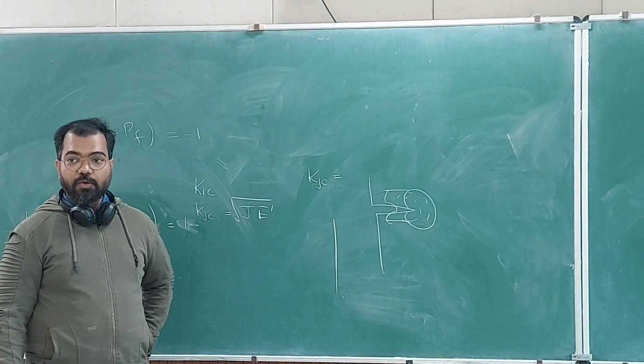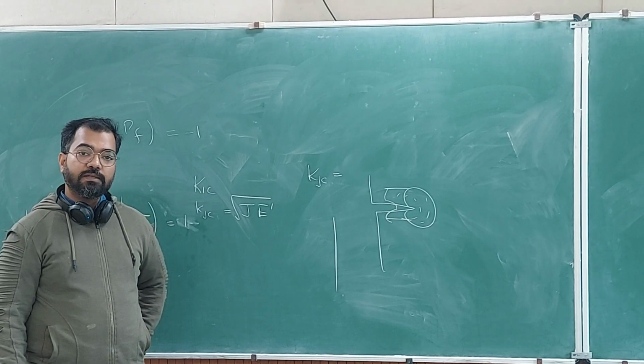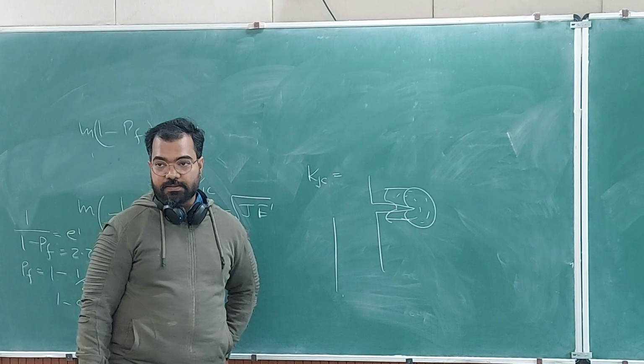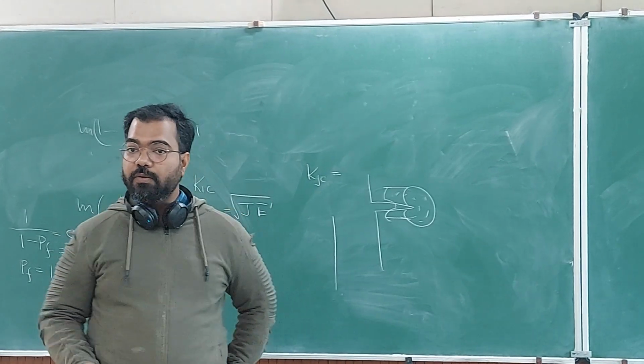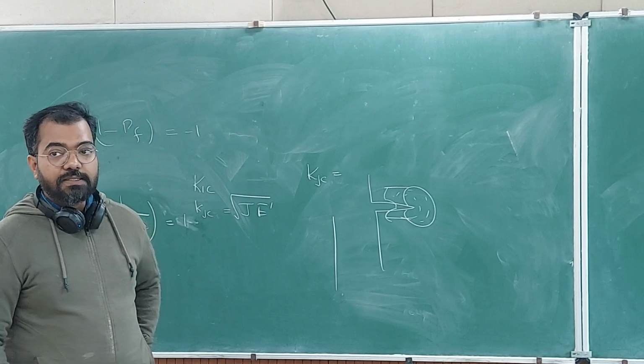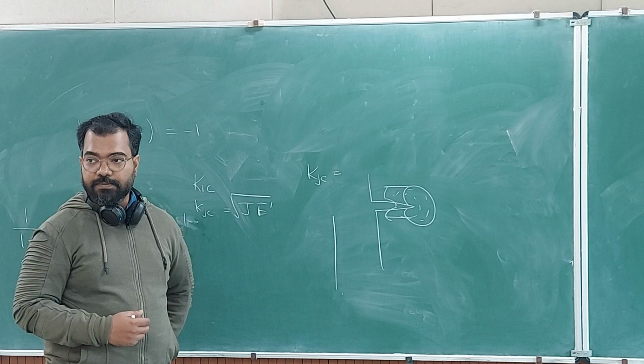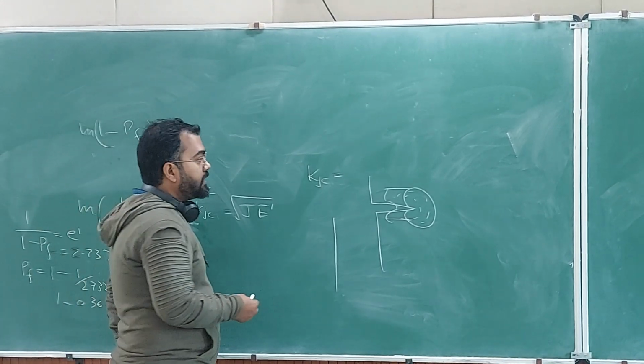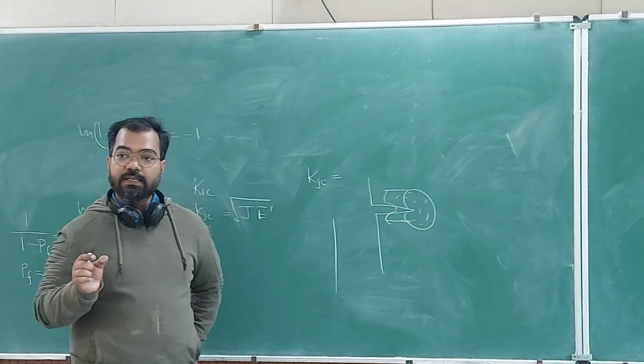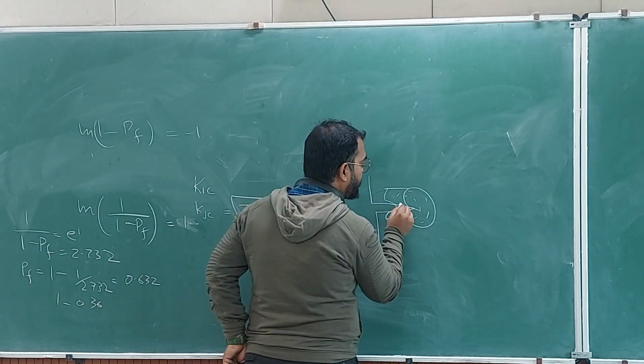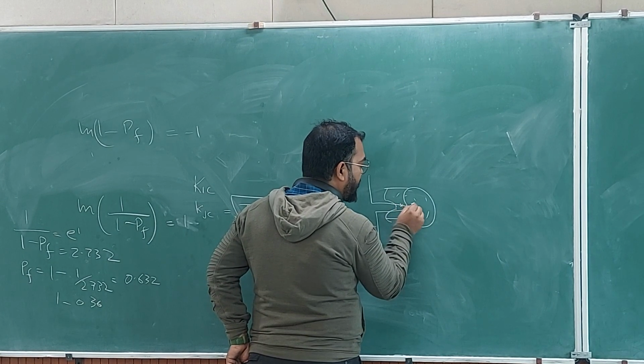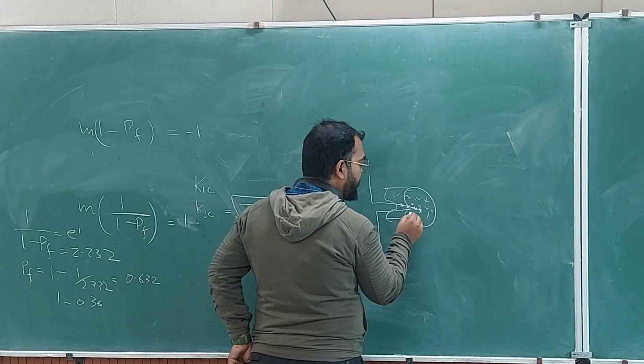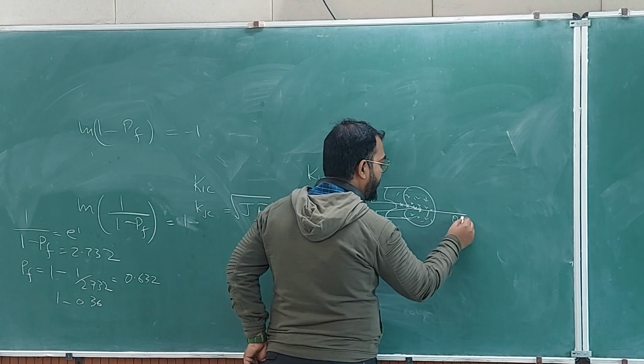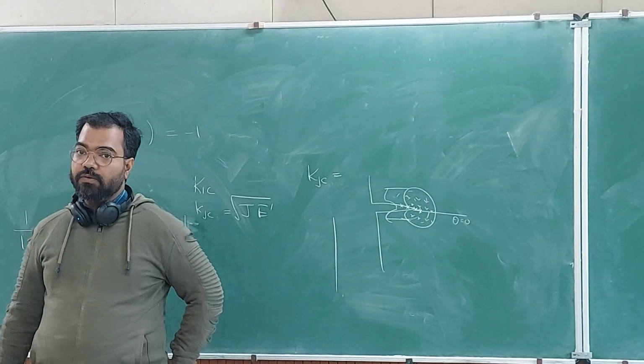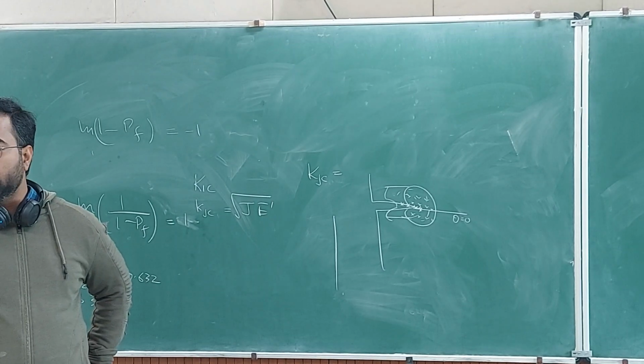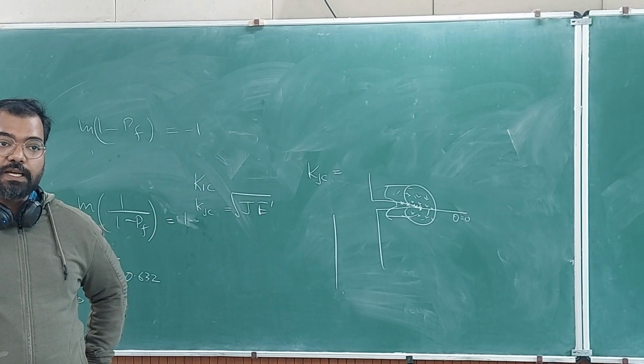Okay, so if you are at lower shelf, all of them probably have the tendency to turn into micro cracks, because the matrix is going to deform in a brittle fashion. As you increase the temperature, the matrix gains some ductility. So then those carbides which are really at the crack front, so let us say that this is the crack front and you have 4 carbides here, and other carbides are lying away at certain angle and also on the theta equal to 0 plane. So those which are exactly at the crack tip might have the highest probability of turning into micro cracks.